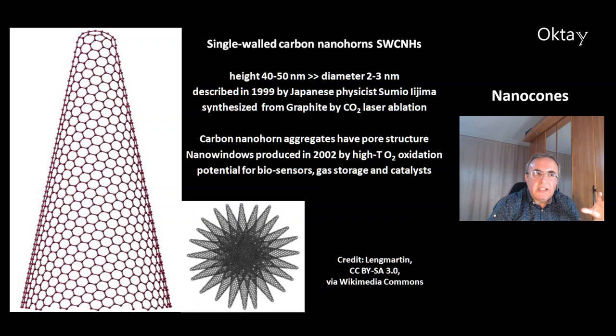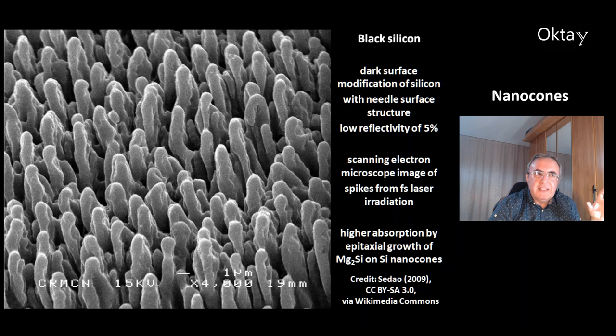Carbon nanohorns can aggregate, giving a pore structure. Nano-windows can be made into the nanohorns; these were first produced in 2002 by high-temperature oxidation with oxygen. These compounds have significant potential for biosensors, gas storage, and as catalysts.